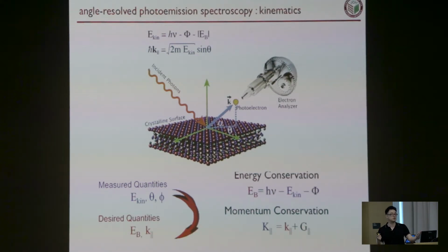It turns out that this is usually the work function of the actual detector itself. That's not physically so interesting for our experiment. The other thing is that if we're measuring a metal, there's a well-defined cutoff, which is the Fermi energy, so we can use that to self-reference what energy we're studying.